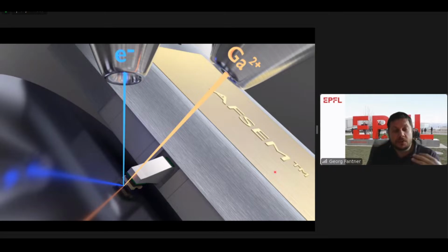And so the AFM has to be very small, has to be easy to integrate. And most importantly, it has to give access to those beams directly to the cantilever, because we not only want to image the same area, but we actually want to image the same area at the same time. And that was a tough challenge, because normally we had these laser beams and lots of optics. And all of that space above the cantilever is occupied by the laser deflection. And so it was not possible to add that to a microscope where the top is used for the electron gun and the ion gun.